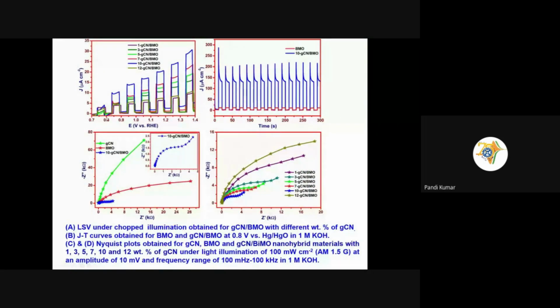The charge separation and migration aspect we have checked by chopped illumination through the linear sweep voltammogram. So here we see the rise and fall in the photocurrent with respect to the increase. Also we have checked the durability. It shows that after several cycles, it has the best reproducibility with respect to time. Then the impedance analysis shows a smaller semicircle, which shows a high interfacial charge transfer rate and minimum charge transfer resistance in the fabricated electrode.